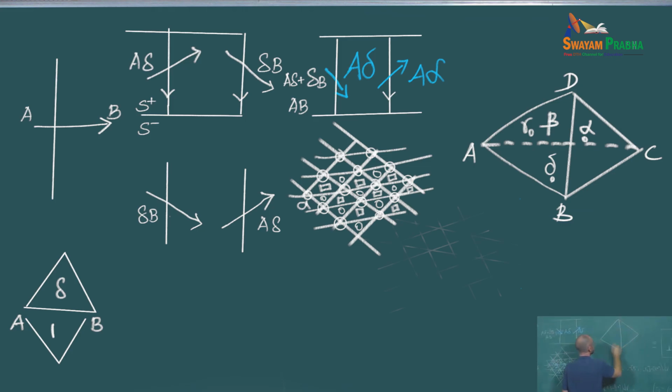But what we said is that in the FCC stacking, if I look at the three positions in one plane and the position in the plane above, it forms a perfect tetrahedron, and I can call the summits ABCD, and then I call the centers of gravity opposite to a summit with the corresponding Greek letters. So I have delta here. Here I have alpha. At the back I have beta, and then at the front here I have gamma.